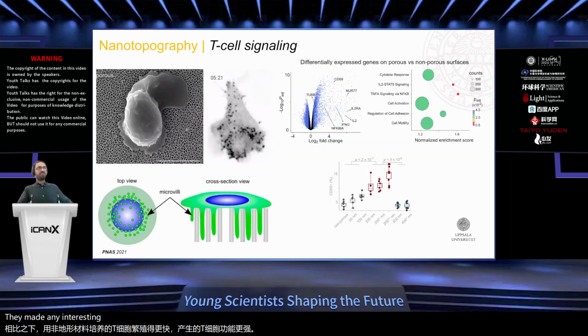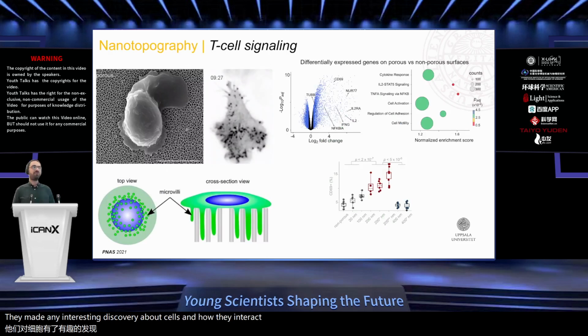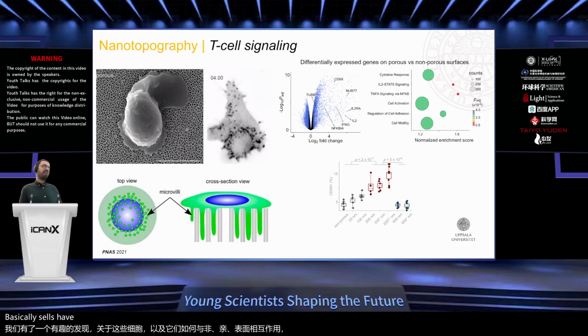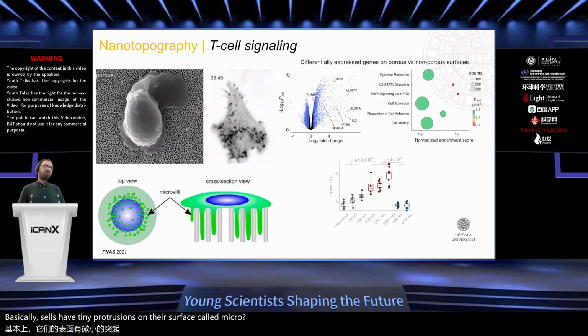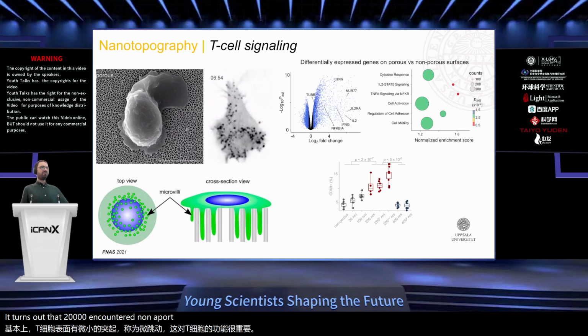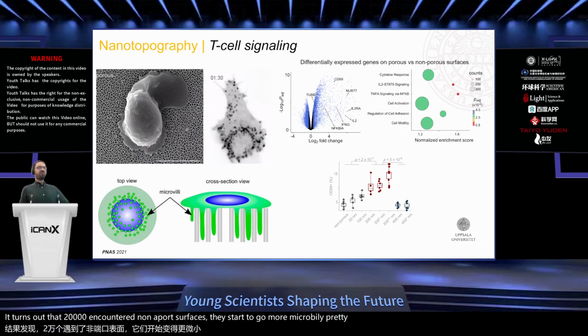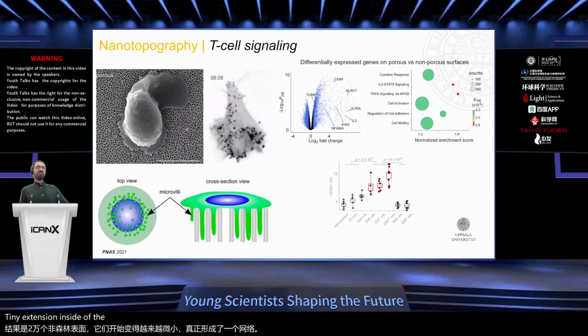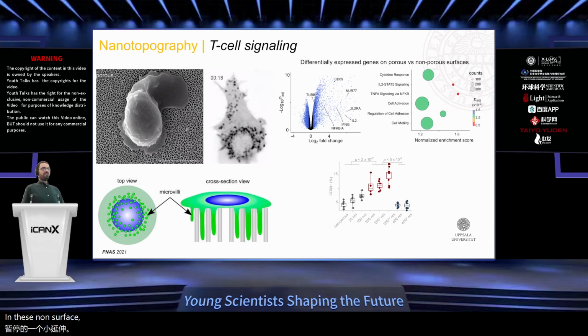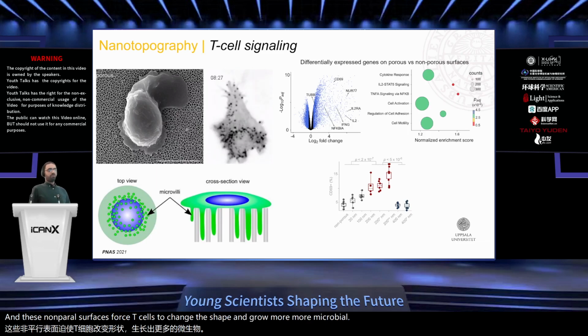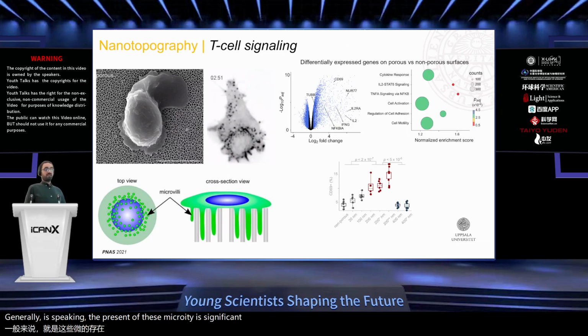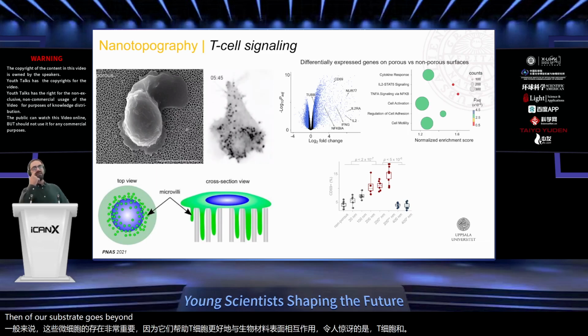We made an interesting discovery about T cells and how they interact with nanoporous surfaces. Basically, T cells have tiny protrusions on their surface called microvilli, which are important for the function of the T cells. It turns out that when T cells encounter nanoporous surfaces, they start to grow more microvilli, creating a network of tiny extensions inside of the pores. And these nanoporous surfaces force T cells to change their shape and grow more microvilli. Generally speaking, the presence of these microvilli is significant because they help T cells to interact better with the surface of the biomaterial. And amazingly, the interaction between T cells and nanoporous substrates goes beyond the formation of these microvilli.